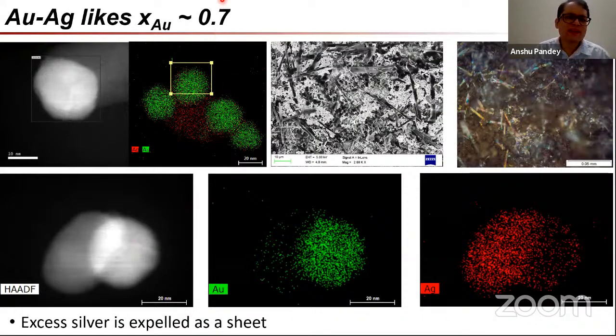So why do I say that there is an island of stability around 0.7? The reason is we have actually tried to load silver more and more. This was interesting for a moment. But what happens very rapidly is that if we try overloading silver into the system, we find that after a few short hours, this silver is actually expelled. So the core of the system returns back to a 0.7 or thereabouts. But it expels the silver apparently in a sheet.